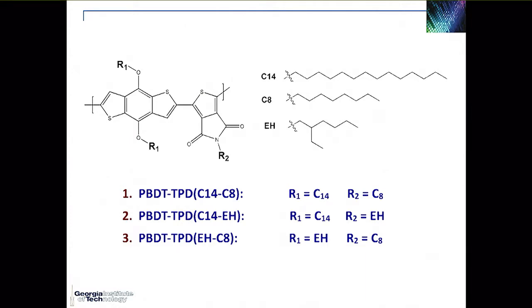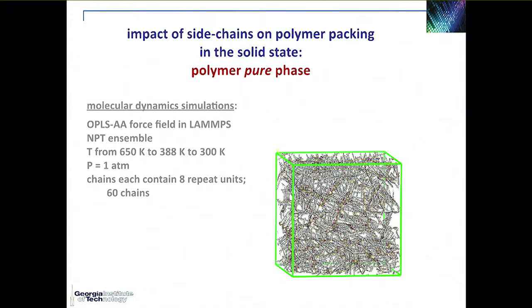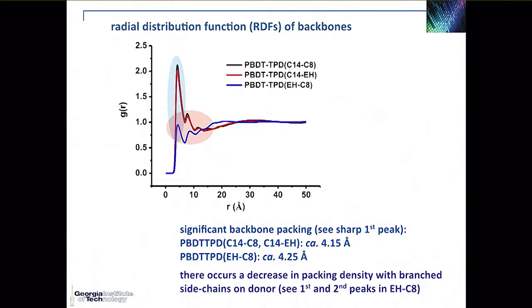In the case of the third polymer, I put the branch side chains on the electron-rich part. I have 2 branch side chains per polymer repeat unit. So I go from 0 to 1 to 2 branch side chains per polymer repeat unit. And that will be important to understand what goes on afterwards. First, we look at the polymer pure phases to see how those polymer chains can pack and the variations in packing that can be induced with the nature of the side chains. And I don't want to go into the details here. We can discuss them afterwards if you so wish.